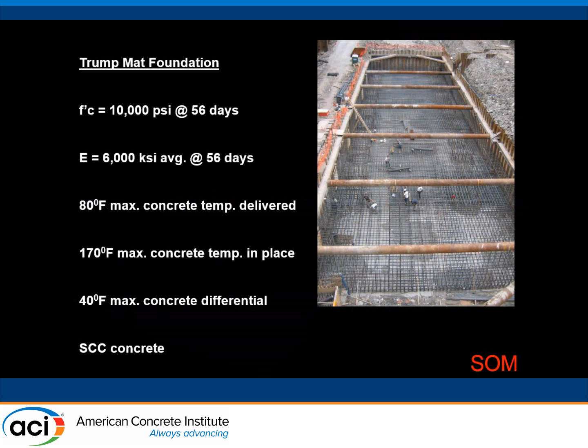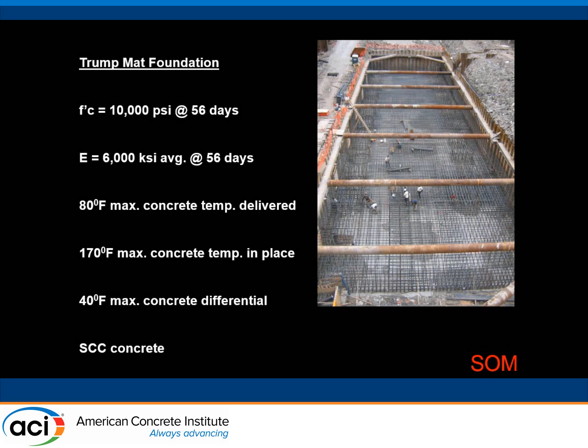Okay, I want to move on to the mat foundation here. We're targeting 10,000 psi concrete for the mat at 56 days. A fairly moderate modulus of 6,000 ksi at 56 days. And because of the mass concrete nature of this element, we specified an 80-degree Fahrenheit max concrete temperature at delivery with 170 max concrete temperature in place. And then also, very important, the differential temperature between the core zone of the mat and the surface. That's perhaps even more important, as we don't want to develop residual stresses as things cool differentially. And we did utilize self-consolidating concrete so that there was no vibration required for such a large tub of concrete.